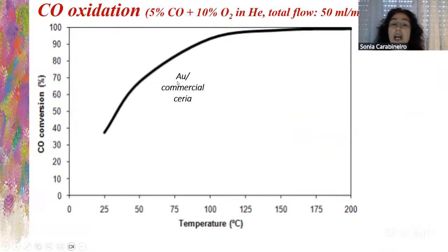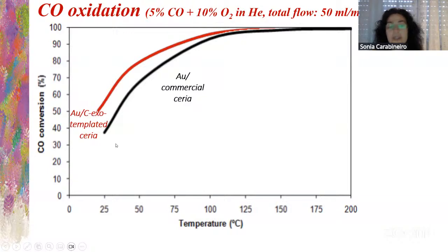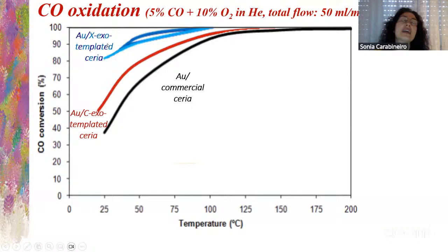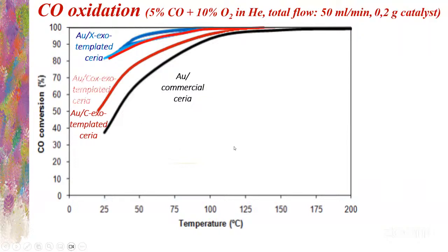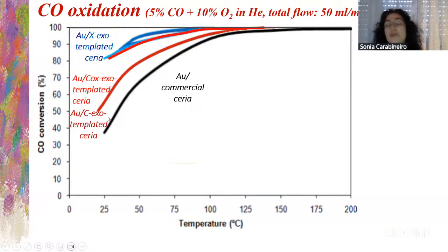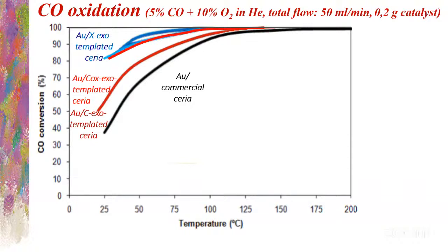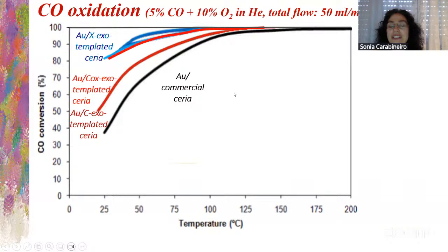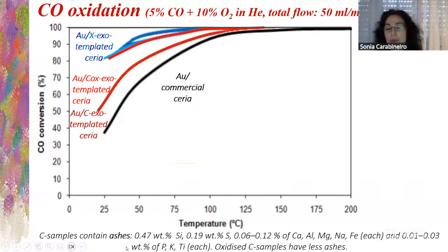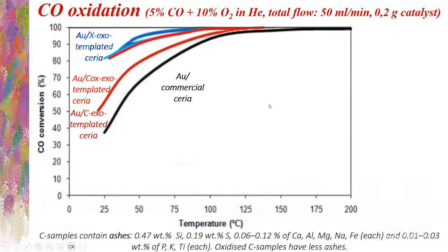Here we have the results for gold on commercial ceria. The gold on exotemplated ceria prepared with activated carbon is a bit better. But if we use cryogel, which is made from formaldehyde and resorcinol put together to form a gel, it doesn't have ashes. And we see that the ashes from the activated carbon decrease the activity. If we oxidize the activated carbon by treatment with acid, we see that the activity is better, similar to that of the cryogel. So here are the results that we obtained for the ashes. The oxidized carbon samples have less ashes.